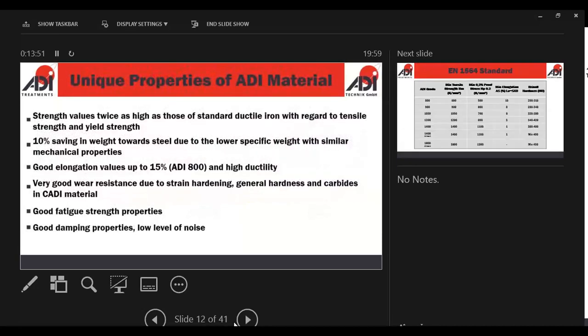So if we do this correctly, as I say, ADI offers a unique combination of mechanical properties. And the whole point of this is really for the iron foundries that are producing ductile iron to go out to the marketplace and say, you're using cast steel, using welded fabricated steel, you're using aluminium in certain cases, we can replace that with this ADI material because we can offer something that's got very high strength, very high ductility, very high fatigue resistance, very high impact resistance.